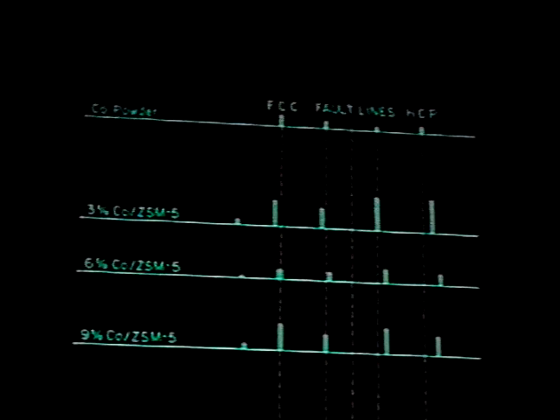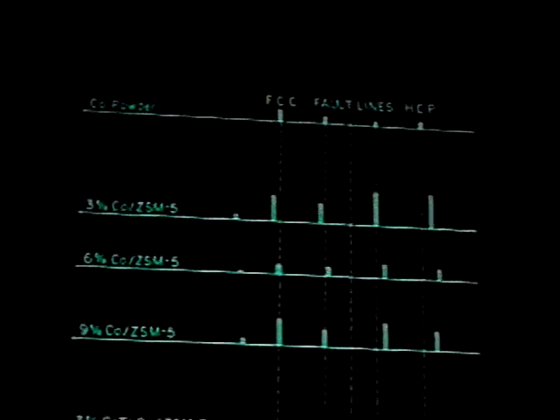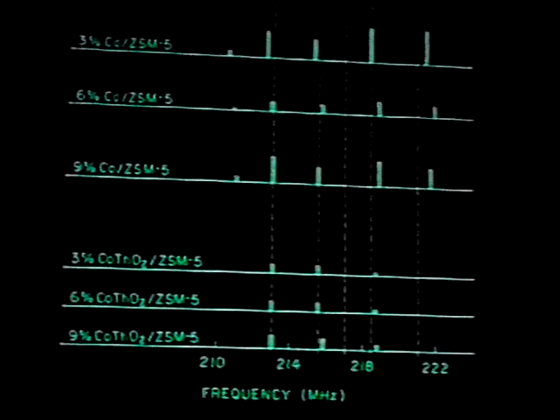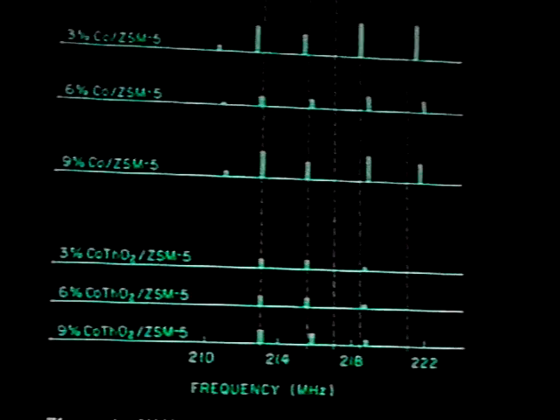In zero field resonance, which is occurring in a ferromagnetic sample, you have what are known as domain walls. You have ferromagnetic domains where the spins in one domain are oriented in one direction, and in the neighboring domain the spins are aligned in a different direction, and in between them you have a domain wall where the spins gradually turn over.